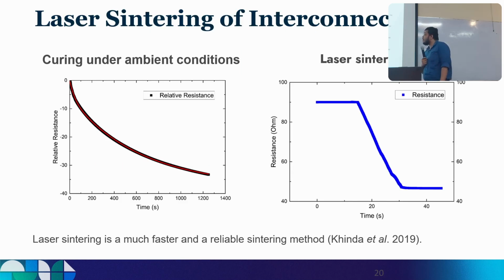Let's discuss a bit about how efficient this laser sintering is. On the left is the resistance of an interconnect which was cured under ambient conditions. That was just kept in the lab, and the real-time resistance was analyzed. And this here is the resistance under laser sintering. We can see that to reduce the resistance by 35% under ambient conditions, it took close to half an hour. Under laser sintering, it was done in nearly 20 seconds. And even the reduction is larger compared to the cure.